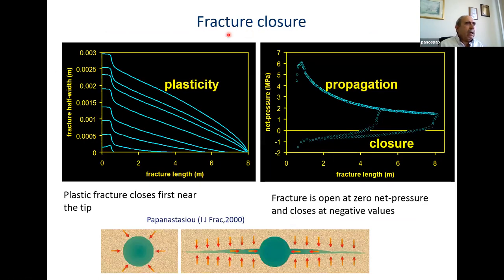Now I will look at the fracture closure. So again, with the plasticity solution, we propagated the fracture and it reached that fracture profile, which I show here. You can see the last line. And then I will allow the fracture to close down. And this is the fracture profile. As the fracture closes, you can see that it closes quite a lot. Almost half of the volume closes without changing the fracture length. And then the fracture closes like in a zip pattern. It closes first near the tip, and then the closure lasts near the wellbore.